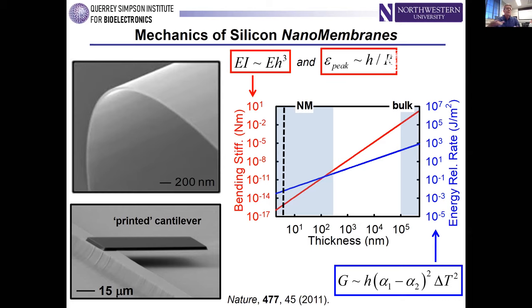So you think about a silicon wafer, it's partly rigid and brittle because silicon is a high modulus material intrinsically, but it's also because the wafer is pretty thick. It's like a millimeter in thickness, maybe a half millimeter in thickness. And by making any kind of material structure very thin, you can reduce the bending stiffness very significantly because the bending stiffness scales like the cube of the thickness. So if you go from the thickness of a wafer, maybe a millimeter, down to the thickness of what we'll refer to as a nanomembrane, where the thickness of the material structure is maybe 100 nanometers or 10 nanometers or something like that, because of that cubic scaling, you can reduce the bending stiffness by 14, 15 orders of magnitude. And it's just Newtonian bending mechanics that's really governing that reduction.